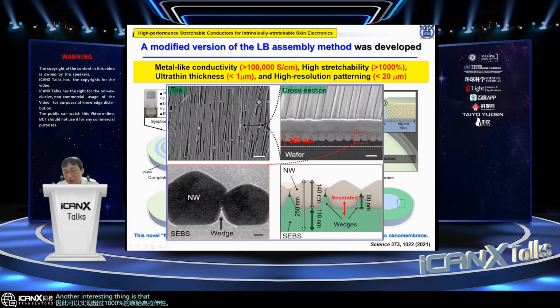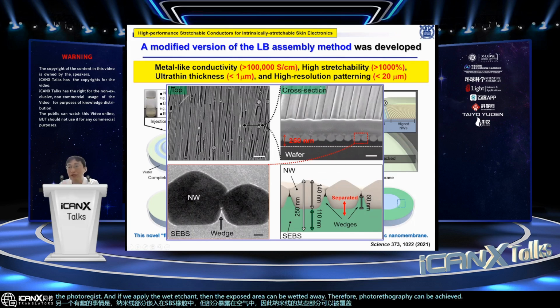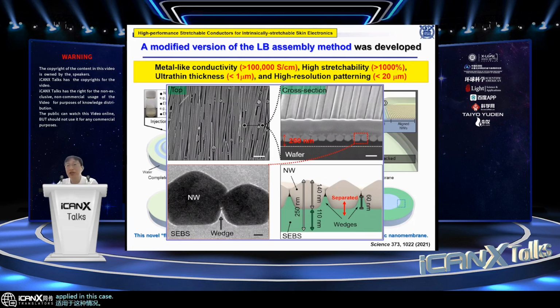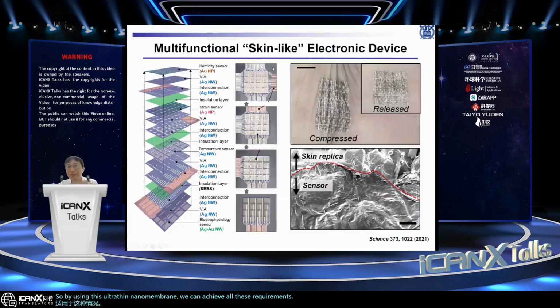Another interesting thing is that nanowires are partially embedded in the SEBS rubber, but partially exposed to the air. So some part of the nanowire can be covered with a photoresist, and if we apply the wet etchant, then the exposed area can be etched away. Therefore, photolithography can be achieved. Therefore, high resolution patterning can be applied in this case. So by using this ultra-thin nanomembrane, we can achieve all these requirements simultaneously. And by using this nanomembrane, we could develop multifunctional skin-like electronic device as shown in this image.